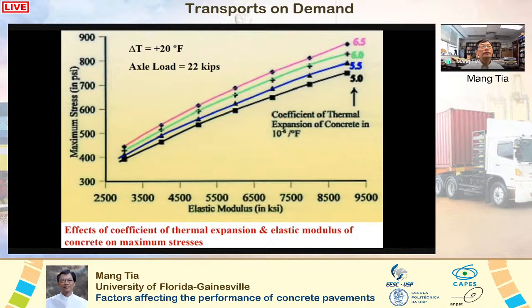This figure shows plots of maximum stress at the critical loading condition as functions of elastic modulus and coefficient of thermal expansion of concrete. When temperature differential in the concrete slab is considered, the maximum stresses are also affected by coefficient of thermal expansion, as you can see from the plot here. As the coefficient of thermal expansion increases, the maximum stress increases, and also it increases as the elastic modulus increases.